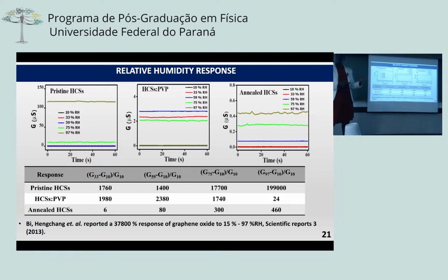This is because the polymer plasticizes, it swells above 60% relative humidity, and therefore bars the water molecules from reaching the electrode surface, and therefore this resulted in this. For the anneal, there was a drastic decrease in the response towards relative humidity. This is because annealing removed the surface functional groups, and also it removed the presence of amorphous domains.